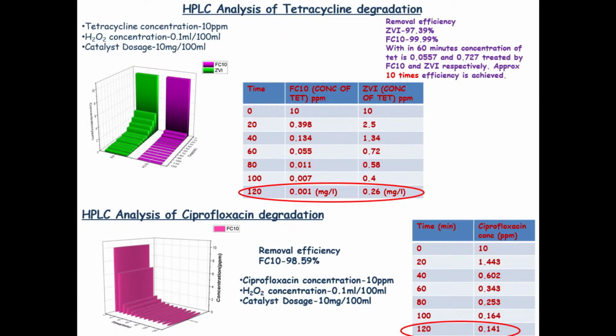Now, to give a more quantitative idea of the results, HPLC, or high performance liquid chromatography, is one of the important techniques which can tell us the removal efficiency of these antibiotics. You can see that the heterostructure has about 99.9% removal as compared to 97% for ZVI. So it's almost 10 times more efficient. It is also much more stable as compared to ZVI. Along with tetracycline, ciprofloxacin also shows a very high removal efficiency.